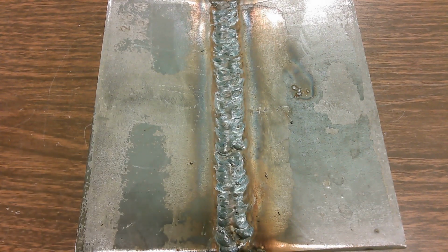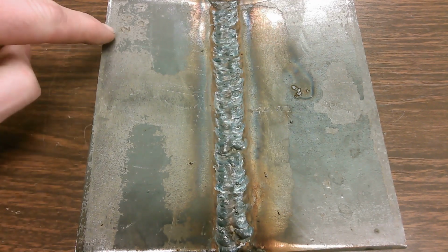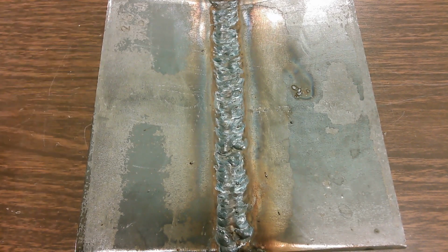Okay, here's another example of a vertical plate. This was a 3G vertical. This plate was actually fitted up and stamped as a 2G. However, it was a V-groove instead of a single bevel, and we just rotated it and used it as a practice plate for a 3G. This doesn't count towards a test because the original root pass was actually run 2G, and then I said, wait a second, that's the wrong fit up. We've got to fix that.